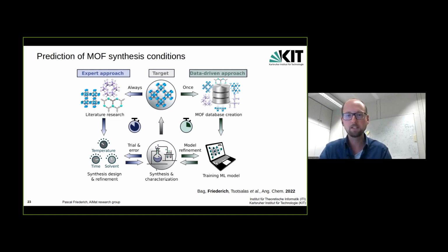So we created the first MOF synthesis database. Of course, there's loads of different MOF crystal structure databases out there, but we were using an automated extraction protocol that was going through thousands of papers, extracted all the relevant synthesis conditions for a lot of different known MOFs, and created a database, and then trained a machine learning model on the database that can map from the MOF input structure to the optimal synthesis conditions. So it uses just the CIF file basically as the input, as the structure, and predicts what is the optimal temperature, what is the optimal solvent, what is the optimal time to run that MOF synthesis.